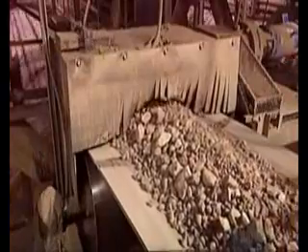From there, the powder moves into a rotary kiln, a huge cylindrical furnace. It's set at an angle so that the powder moves from top to bottom a distance of 49 meters. The kiln rotates about two turns a minute to ensure the material travels through at the right speed. The burner's gas flame at the bottom reaches a scorching 1,600 to 1,700 degrees Celsius. As the powder approaching it reaches the 1,500 degree mark, it fuses into pieces about the size of marbles — these pieces are called clinker. As the clinker leaves the kiln, large fans cool it down to between 60 and 80 degrees Celsius. It's important to cool the clinker quickly in order to have quality cement. From here, the clinker goes to the storage area.